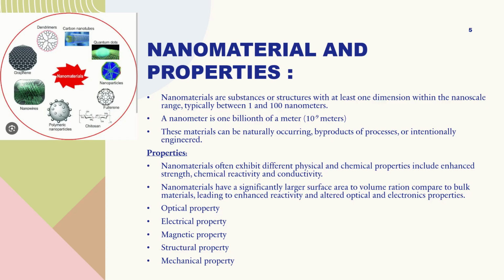If the size of the material is less than 20 nanometers, absorption is significant, and if the size is greater than 100 nanometers, scattering is significant. Thus, by designing nanoparticles of different sizes, an optimal amount of absorption or scattering can be achieved.